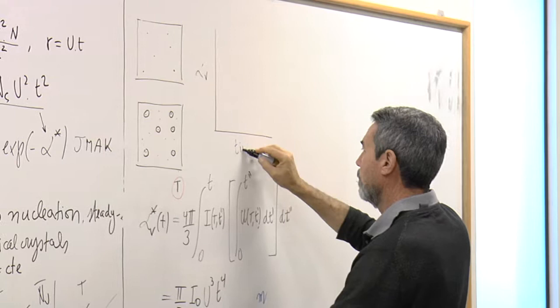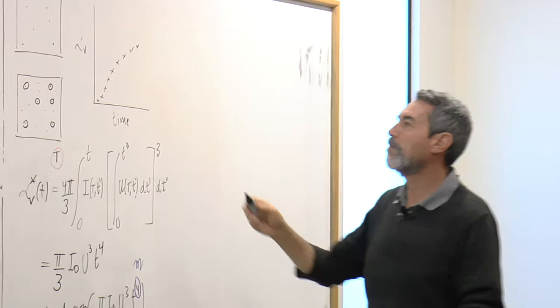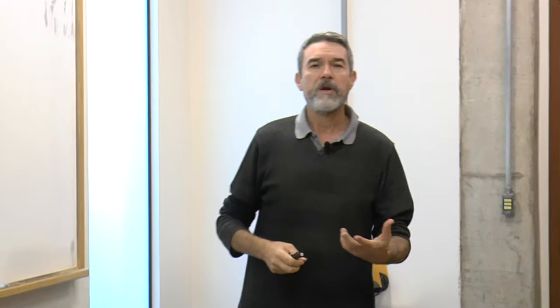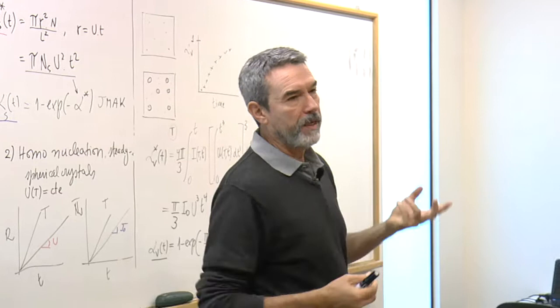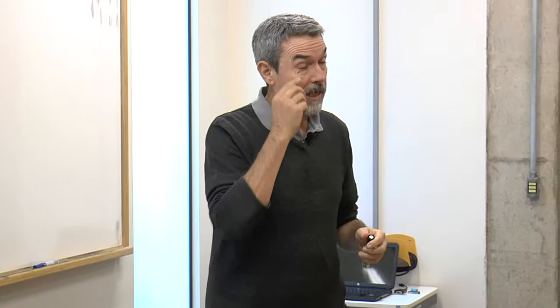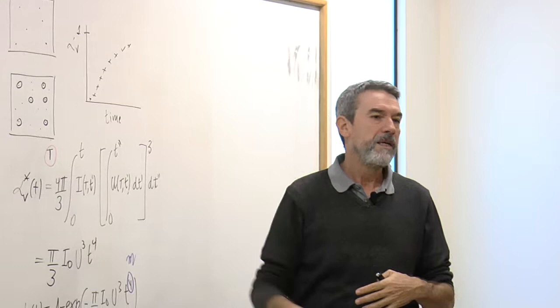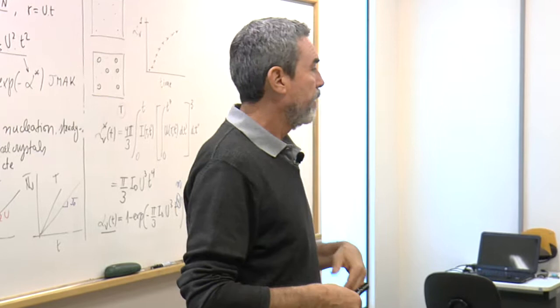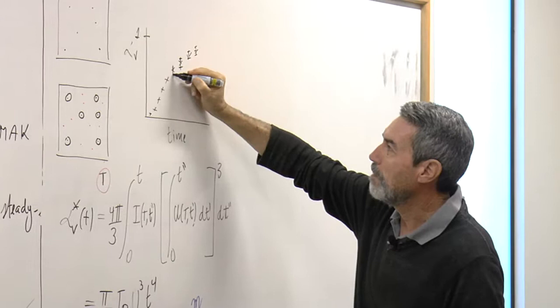and somehow measure the evolution of crystallinity as a function of time by some technique. There are several techniques. Every technique is more or less adequate to a particular problem. For instance, if your crystals are nanometric, you have to use electron microscopy techniques. If the volume fraction is very small, you cannot use DSC techniques. DSC techniques are good for high volume fraction. If the particles are larger than 5 microns or so, then you can use even optical microscopy. X-ray diffraction techniques, there are many techniques which can be used. Of course, all measurements have some error, and you have some error here.